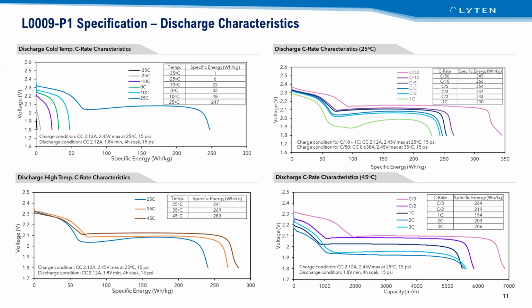That SEI layer is a continuing chemical process, and it eats lithium and it eats electrolyte and other things. We're finding with this cell chemistry, actually, we get very good calendar life, which surprises people. Lithium sulfur traditionally has been thought of as very poor. What we found is once you make that passivation layer, the cell is very, very stable. So it sits at 100% state of charge, at high temperature, low temperature, doesn't matter.